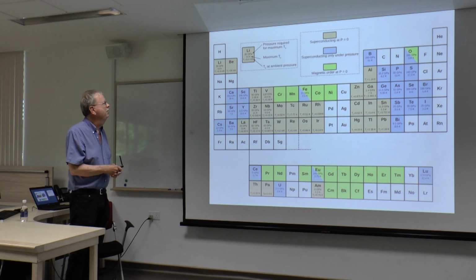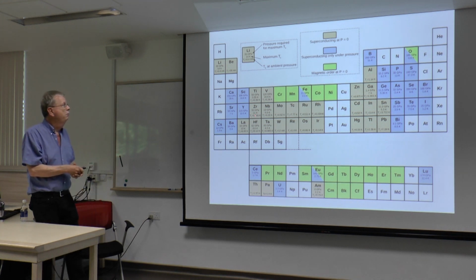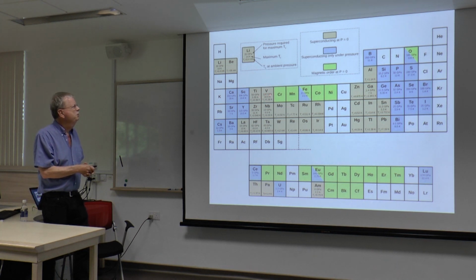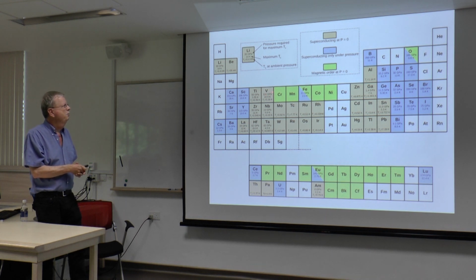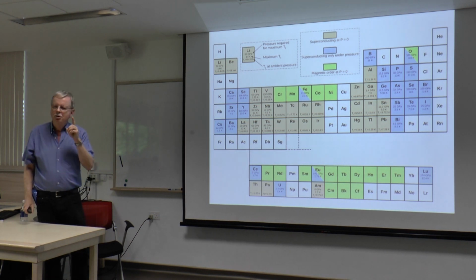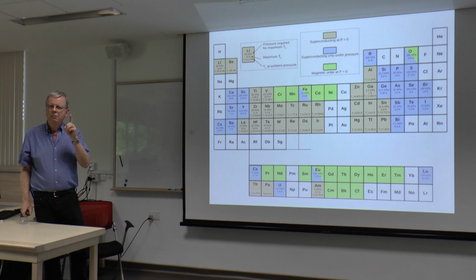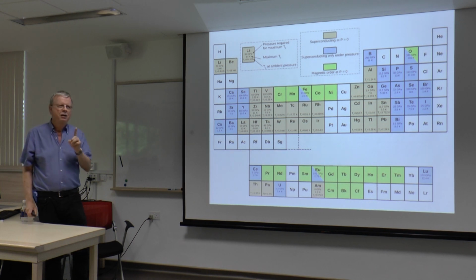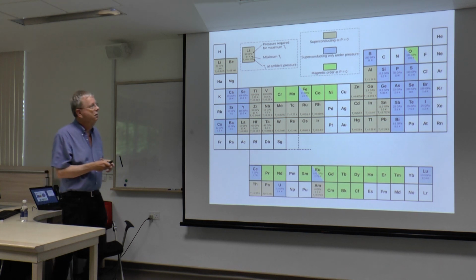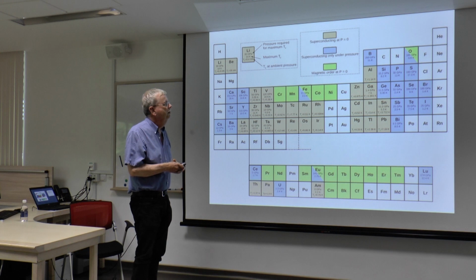But anyway, if you try to read it carefully, you can see that you can raise the TC of vanadium, which at room pressure is sort of like a 4-degree superconductor. If you go up to 1.2 megabar or 120 gigapascals, whatever you're most comfortable with, you can get a TC up around this number. Matthias liked to say, no theorist ever predicted a real superconductor. And just after he died, in '81, Marvin Cohen at Berkeley published the prediction that if you put silicon under pressure, it would superconduct. And he got it mostly right.